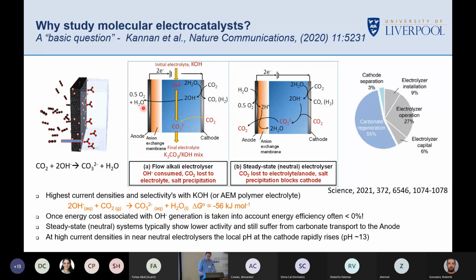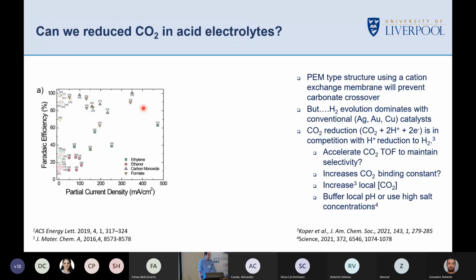The other point about the near neutral systems is that, of course, at high current densities, we're consuming the protons at the electrode surface, whether we're doing CO2 reduction or proton reduction, and the local pH will jump up. So we'll get carbonate formation even at the cathode surface, even if the bulk pH is lower. So can we just do it in acids? And there's some really nice work on this coming out, and it's starting to appear.